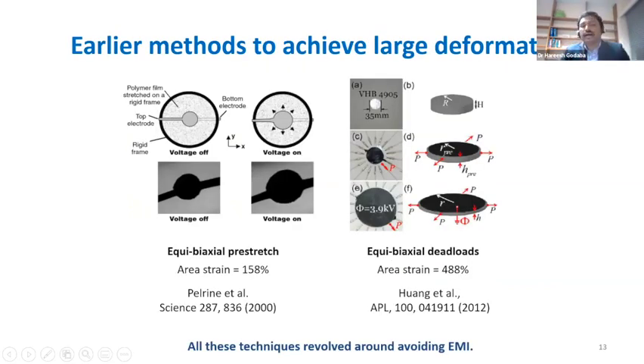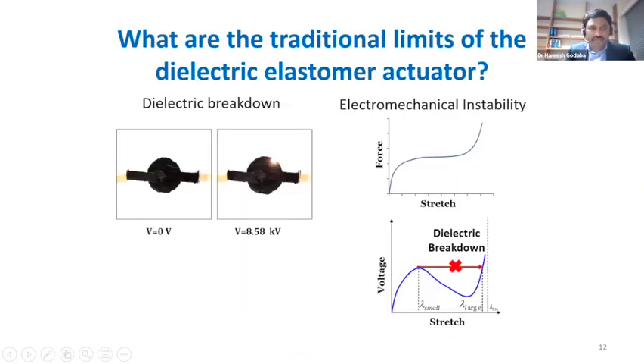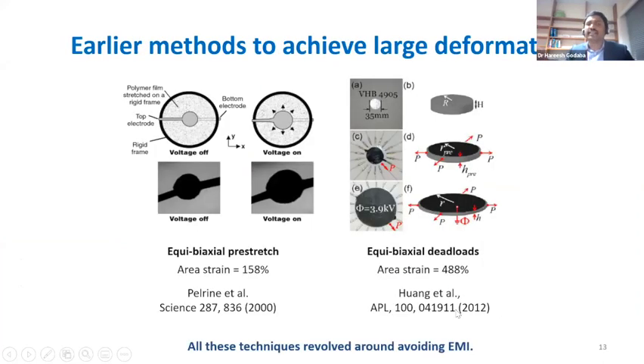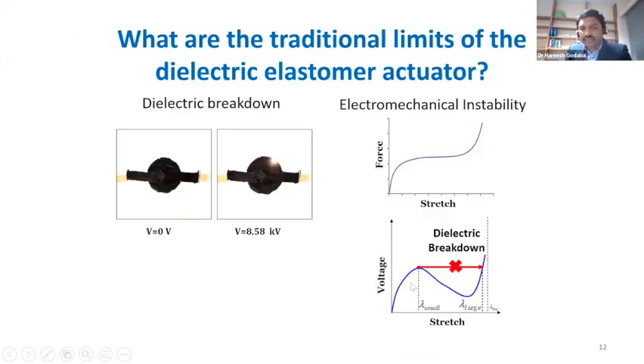Then people tried to look at different ways to increase this actuation strain, and people found that if we apply some initial pre-stretch, either by stretching the membrane and clamping on a frame, or by applying some preload, which will keep the initial state of the membrane slightly larger than 1.3 stretch, then this nonlinear curve becomes monotonic, and you can go all the way until breakdown. So you can achieve a much higher actuation strain. People found that you can achieve more than 100%, and in this equibiaxial case, you can achieve as high as more than 400% areal strain. But these techniques are generally about avoiding this type of N-shaped curve, basically avoiding this instability called electromechanical instability.